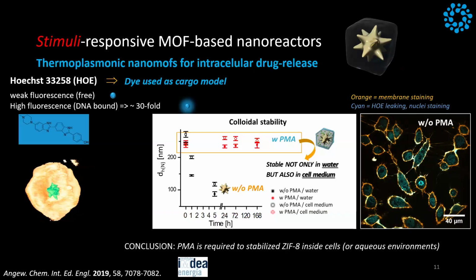and we used an amphiphilic polymer that we have been using for 20 years. It's PMA. We call it PMA. It has a hydrophobic chain and hydrophilic tails. And basically, we coated the MOF, and then with this coating, we prevented the degradation, and the MOF was stable for weeks, for months. But we had to put a polymer coating on top of a MOF. That is not something that I wanted to do. We did it, and then it is stable in very acidic conditions, in media, mimicking the kind of environment that you have in the lysosomes and these things. In water, in cell medium, and so on.